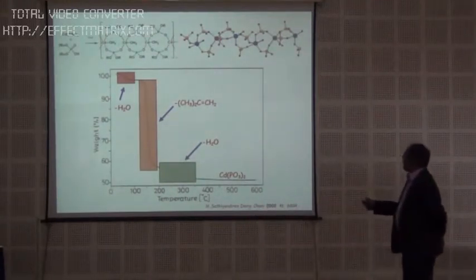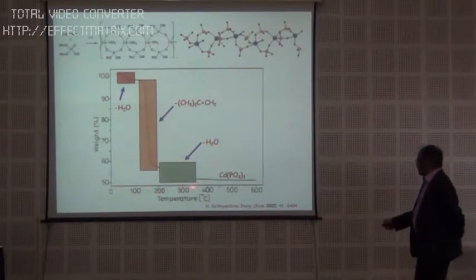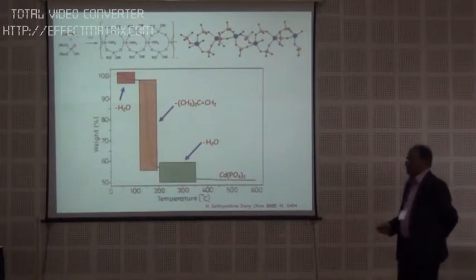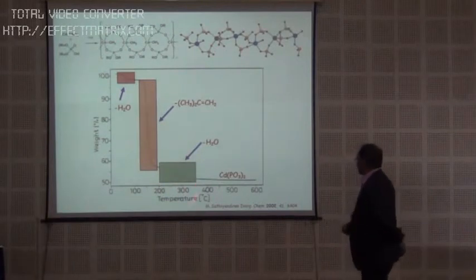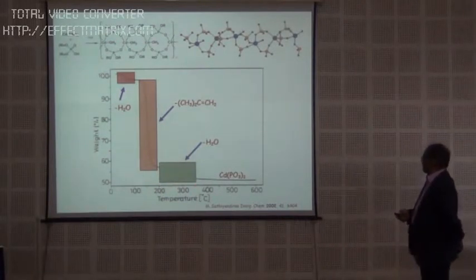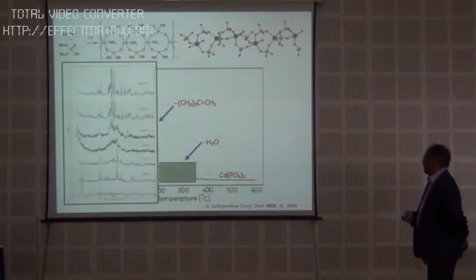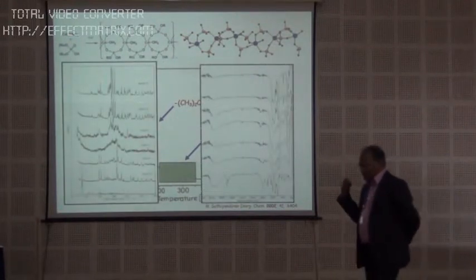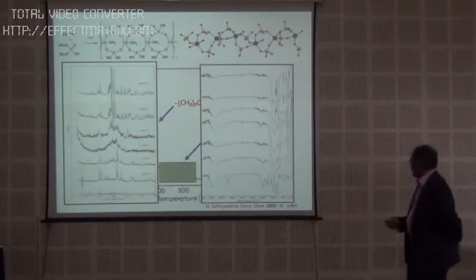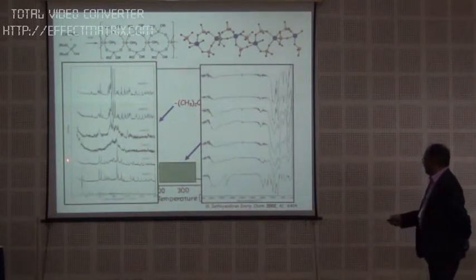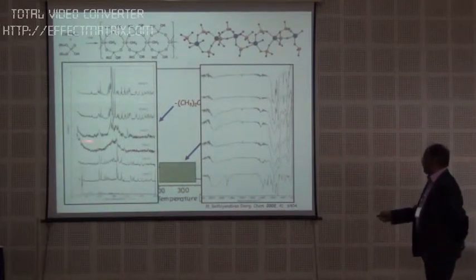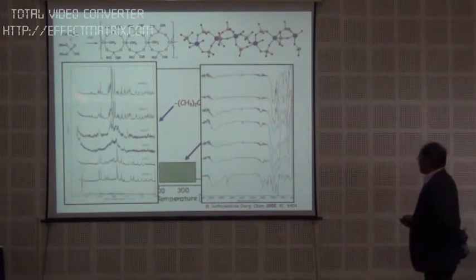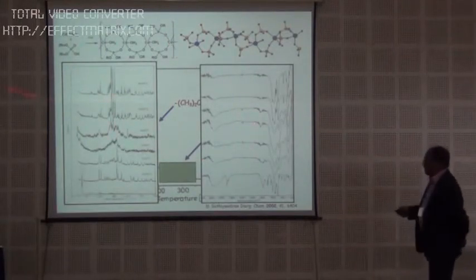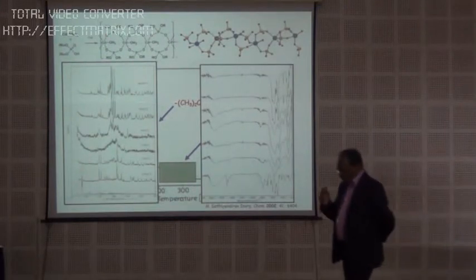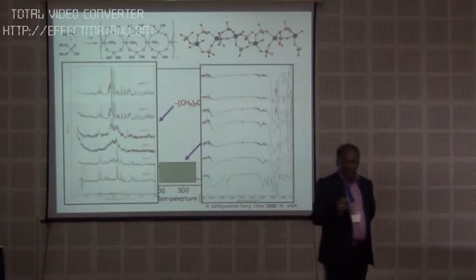Then the condensation of the surface P-OH groups takes place between 200 and 300 degrees centigrade, and you are in business at temperatures as low as 300 degrees centigrade. You can do this with essentially every metal in the periodic table, and you can follow these reactions by in situ X-ray diffraction or in situ spectroscopy. It could be phosphorus NMR, it could be infrared. As you can see, this is a metal organic polymer, you get an inorganic polymer, then it condenses, and at 350 degrees centigrade you have the nanoscopic phosphate, then this crystallizes. So the theme of the entire work was to make condensed phase materials, often in the size regime of somewhere between 5 to 20 nanometers.